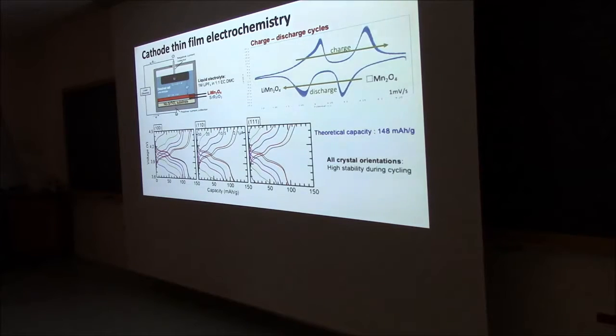And I'm kind of surprised that if it's confined on a substrate, that you can fully delithiate. Yeah, so the point is that the A and B directions of the material are aligned with the A and B directions of the substrate, but they're not epitaxially strained. But it's still clamped on there. Yeah. Right? So there has to be some elastic part. I guess to keep it fully. Yeah, I don't know the number off the top of my head, but I'll show you later on. We can go more extreme, and we can deal with strain better than what's normally done in bulk.